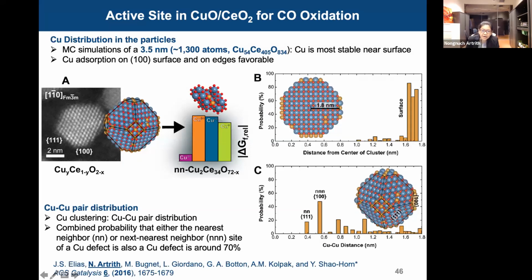And when we see where the structure is and how the atoms look, we take from the model the phases, and then use DFT calculations to find what could be the most stable structures, and then we can use DFT to find the oxidation state, which is where the active sites are. So this is also very useful, using neural potentials to help find the active sites of the structures.